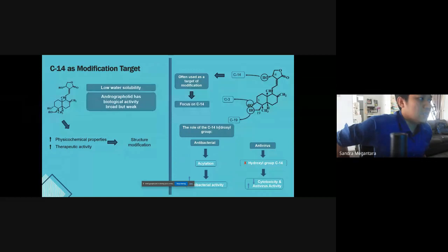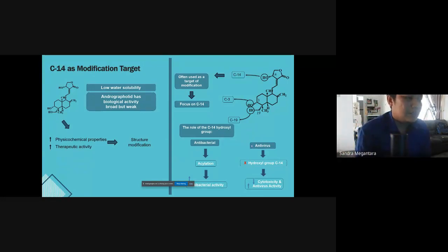Now we focus on C14, which is often used as a target of modification. Why? Because the hydroxyl group at C14 is good for antibacterial activity. But if we change the hydroxyl group with a non-polar functional group, it is good for antivirus. As we know, antivirus is still the same as aspartate protease inhibitor, like in plasmepsin. If we delete the hydroxyl group in C14, we get better cytotoxic properties, with lower toxicity, and antivirus activity is increased.